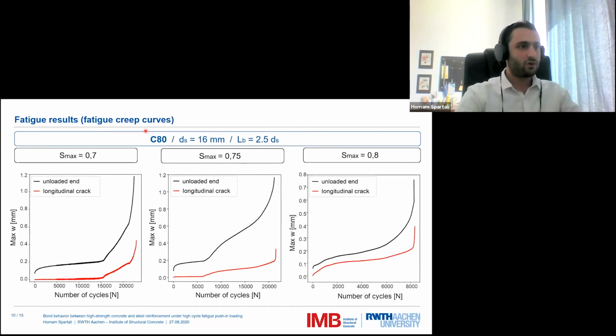In the case of concrete C80 with these parameters, we tested 3 different maximum load levels. And it's to be noticed here that in the first load level, we saw the splitting crack in the second half of the fatigue lifetime. And in this load level of 75%, it was observed in the first half of the fatigue lifetime. And in this case, the highest case, it was observed directly from the beginning, as we see here from the